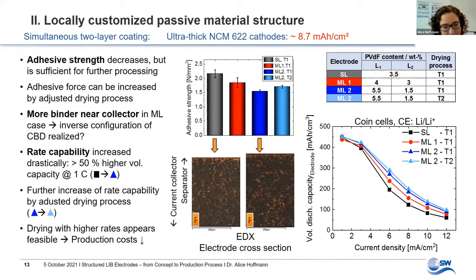To analyze the electrochemical benefit, the volumetric discharge capacity in half cells is shown here as a function of current density. By the two-layer coating, the rate capability was increased the higher the difference of binder content in the suspensions was. And with an adopted drying procedure, seen here in light blue, a further increase of power was reached. And here 8 milliampere per square centimeter corresponds to a rate of 1C.